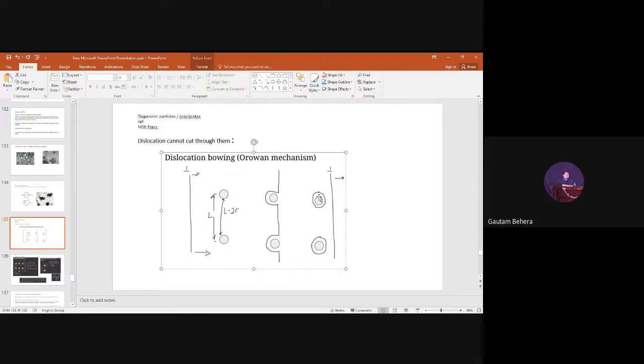But the result is what you can see. The distance between the particles is decreasing now. Why? Because of the formation of a loop. So the distance between the two particles is now from this loop to this loop. Suppose any other dislocation comes, it will form another loop, right? And the distance between the particles decreases again. Further, when a new dislocation wants to move, it cannot move easily. It requires more stress to overcome this distance. That means you understand the strength increases if L minus 2r decreases.